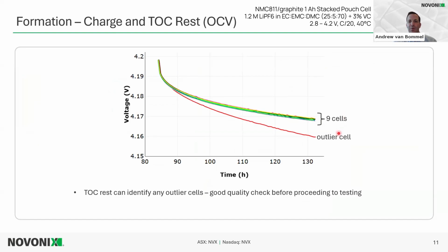The reason why we have more cells here, so usually we test in triplicate, but with our formation procedure, we usually have more cells that are being formed because those cells are going to different testing protocols. So here are 10 cells that are tested, and we see that voltage drop during that OCV rest step, during those 48 hours. And 9 cells all fall with the same voltage drop. So these 9 cells are excellent cells. We see one outlier cell here.